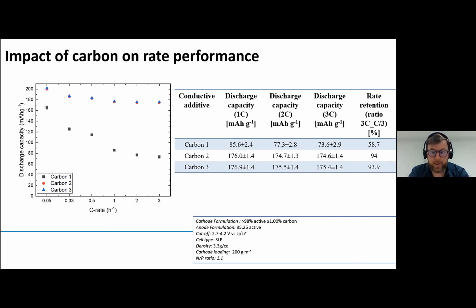This is the same active material. You have a rough guide on the formulations down the bottom right. You're talking 98% active in here. And you see very, very impressive retentions across the different C rates. This is what I mean about the increased capacity. You're looking at the difference between 80 and almost 180 milliamp hours per gram. The same thing, less than 1% of an additive in there, giving this much of a performance boost.